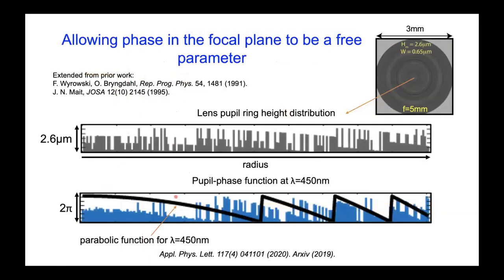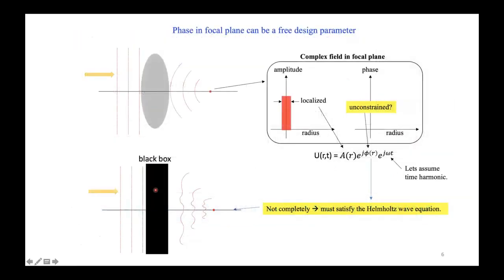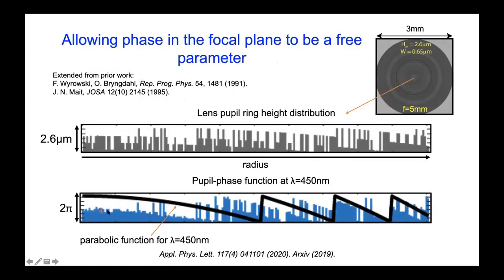Now, if you apply this in a numerical sense, you can come up with very broadband diffractive lenses where the chromatic aberrations have been corrected. And I'm just showing you several examples where we allow the phase in the focal plane to be a free parameter and come up with, in this case, rotationally symmetric diffractive lenses. It doesn't have to be. Where the feature sizes are free varying. These are the heights as a function of radius. And if you look at the pupil phase function, which is basically what goes in this black box, that looks like what's shown in this blue curve for a particular wavelength. In this case, I picked 450 nanometers.